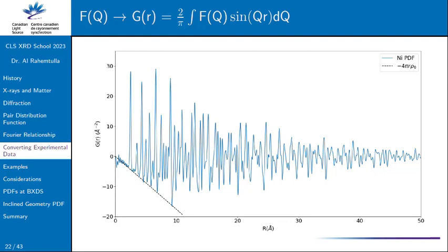If you imagine an atom at the origin, we're looking at distributions of atoms as you go further out in R. Very sharp high peaks are telling us there are very tightly distributed atoms at a certain distance away. As you go further away and see nothing, there's nothing there. See another sharp peak, there are more atoms there. A broad peak is telling us atoms are broadly distributed.